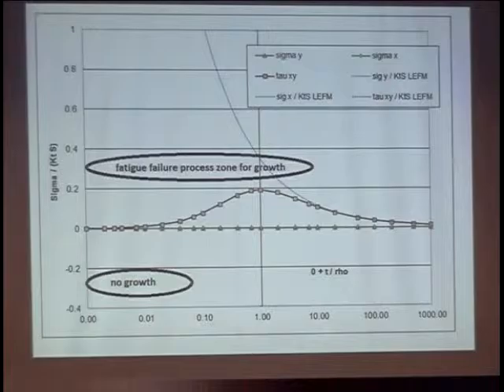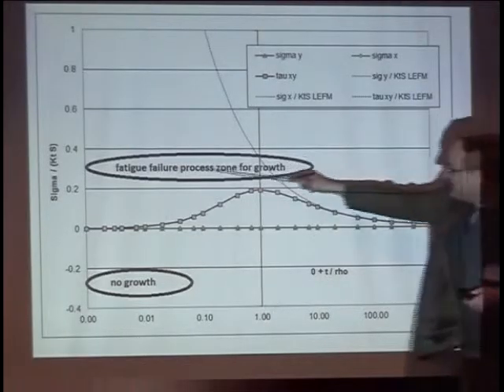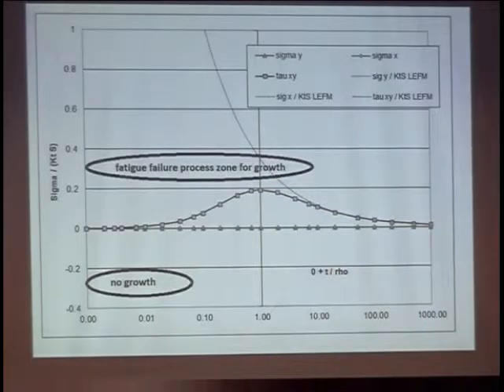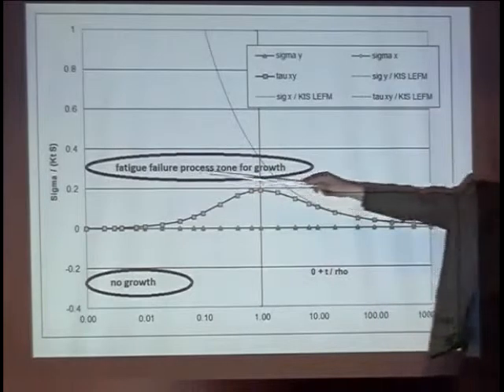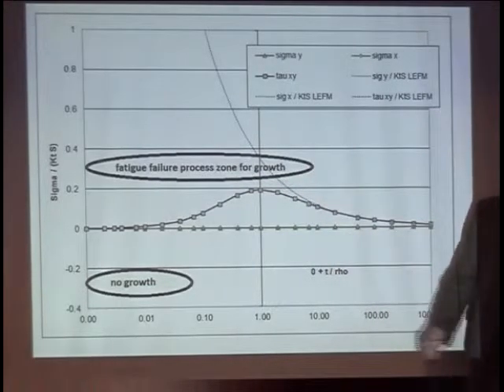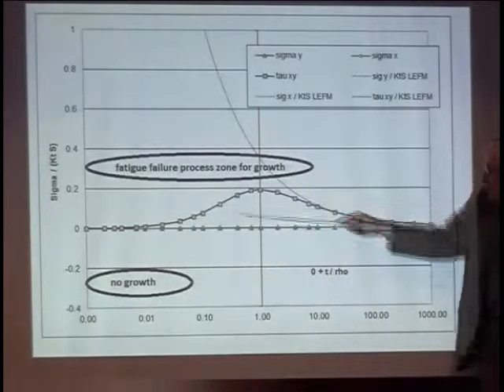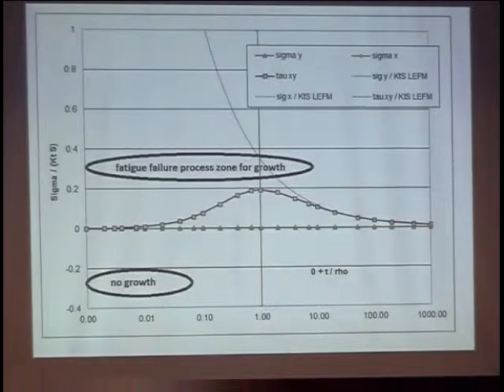First paper I wrote, I think it was years ago, was basically saying there are two parameters, effectively two processes going on. And now I'm just retired and realise that perhaps if there are two processes, they've got a zone each. It's taken me a long time to get there, but there we go. So this is the fatigue failure process zone, which is where the failure process is occurring. The decohesion, if you like, Tompkins model, which I do, or tearing of atoms apart, and all sorts of ideas that came up in the last 2 days, which are actually involved with the failure rather than with the deformation. And so this process zone is rather small. I've sketched one of them here. The figure is exactly the same as we had two slides ago for mode 2.